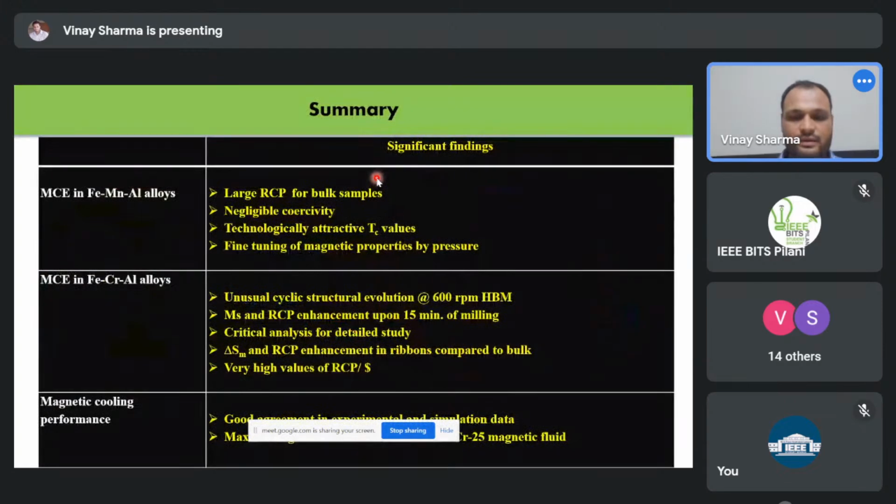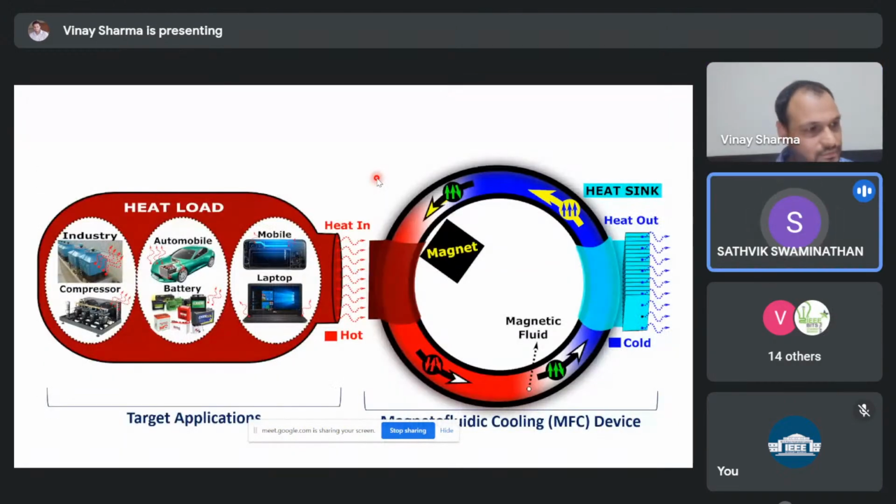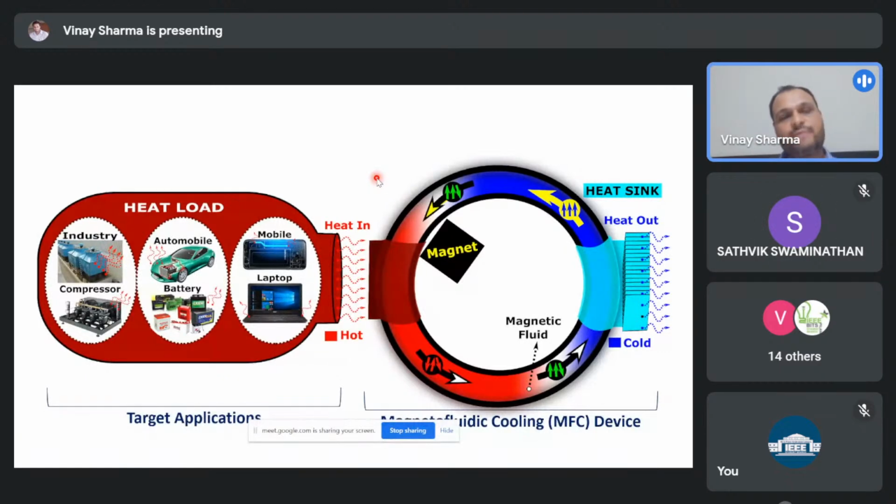Observe, why is it that there's a requirement for the small size of the particles? Because there is something called Brownian motion. If the particle critical size is more than 5 to 10 nanometers, they will start settling down, even though you are using some surfactant or stabilizing agent like polyvinyl alcohol or silicon oil. They won't be stable as soon as a magnet is brought closer to them.